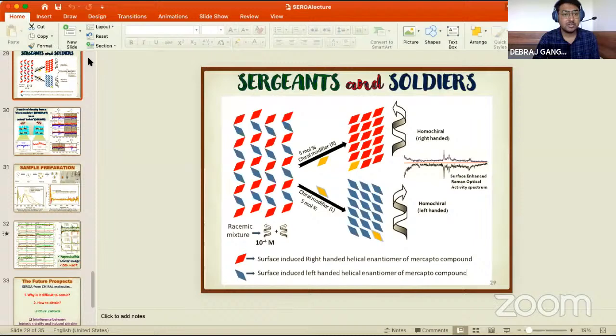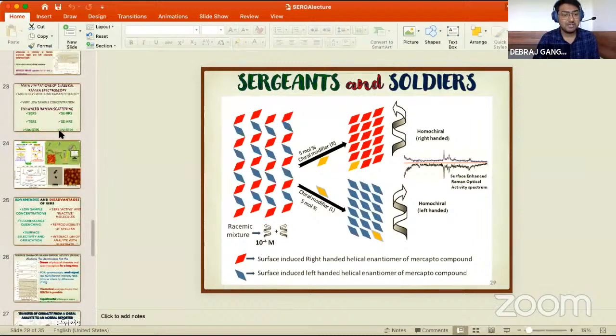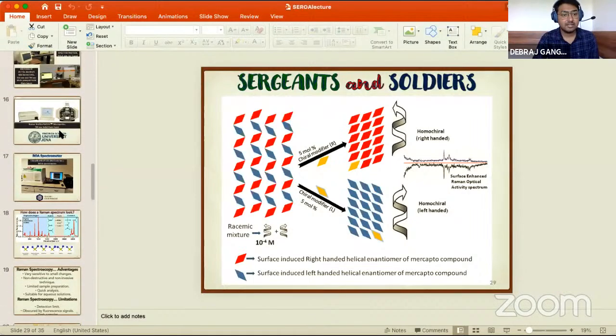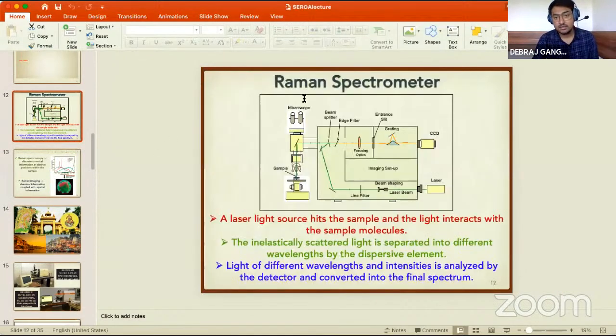As I have shown you, this is the basic structure of a Raman spectrometer. If you can see, you just need to place your sample below the microscope in this kind of Raman spectrometer. In others, where the laser is coming horizontally, you have to place your sample vertically. Mostly that's done for liquid samples. So here you can study solid samples. You just need a glass slide. You put your sample, and it should be flat, and you put it under the microscope, and that's it. The laser will fall on the sample. The sample will scatter radiation, and that scattered radiation will be detected by the detector. That's it. It's so simple, the sample preparation.